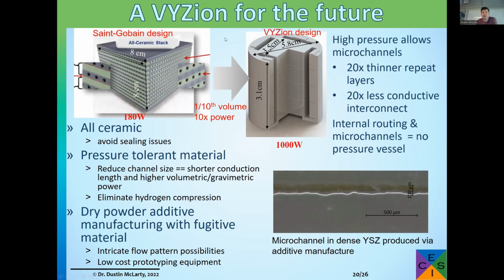The other main difference between Saint-Gobain's design and ours is theirs was designed for atmospheric pressure. So they needed decently sized holes for the gases to flow through. So those holes were, I believe, somewhere around 3 to 5 millimeter diameter holes. And if we're going to go to really high pressure, we can take these channels down to 50 or 60 microns. So we've already been able to demonstrate, and in this picture, you're seeing a sample we cut open and put in this SEM, where we were able to produce sub-100 micron channels that were contiguous and unblocked through an entire component. So we're able to do these fine micro features and do it via printing so we can get into really fancy geometry. And the goal here is basically shrink everything down, less mass, 20 times smaller, all without any high temperature seals to worry about.